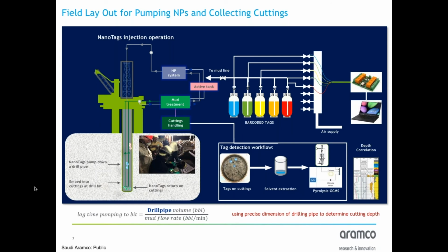So we can do this kind of tagging for the drilling depth precisely without interrupting the drillers or the drilling operation. And later the cuttings, which were tagged as they were drilled at the drill bit, are collected off the shale shaker. After that, the collected cuttings are exposed to a solvent extraction and thermal separation workflow to extract the nanotags from the cuttings in the lab for estimation of arrival times.